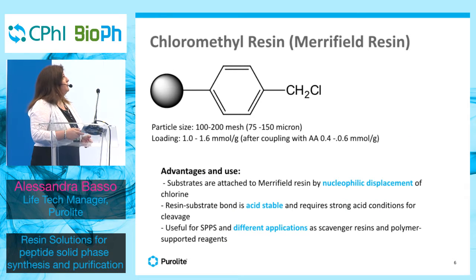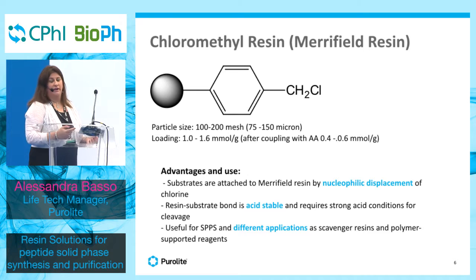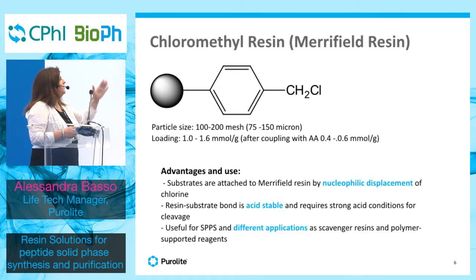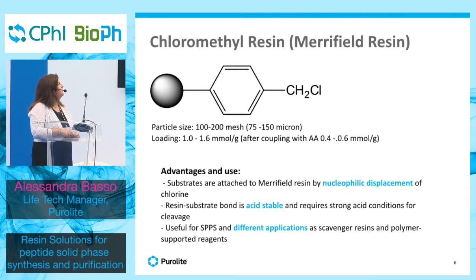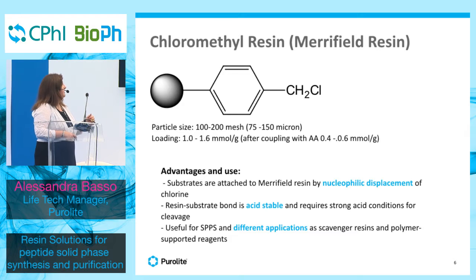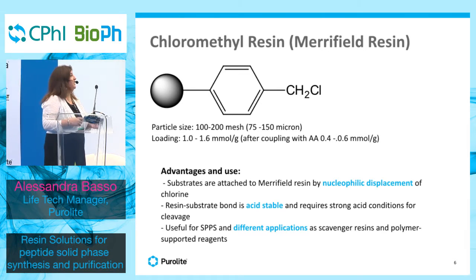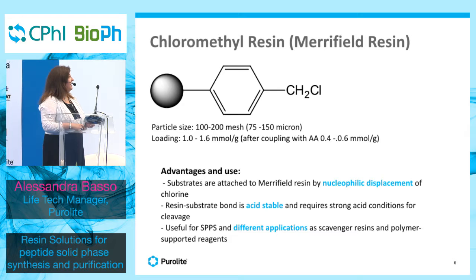The first resin will be a chloromethyl resin, a Merrifield resin that has been on the market for more than 30 years. It will have a particle size of 75 to 150 micron with a loading of 1.0 to 1.6 millimoles per gram, which allows, after the coupling of the first amino acid, a loading of 0.4 to 0.6 millimoles per gram. What is nice about the Merrifield resin is that it is very versatile: you can use it for nucleophilic displacements of chlorine, it is very reactive, the resin is very stable, and it is used for many different applications, also as a scavenger resin, because the chlorine can be used for coupling different compounds.